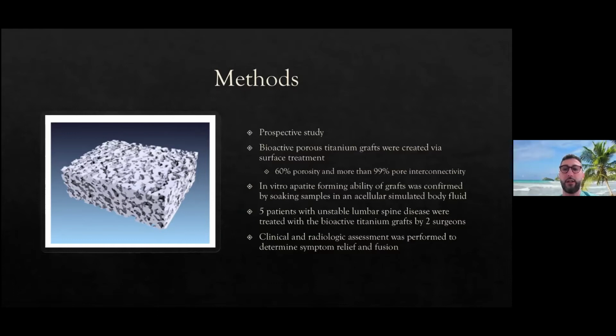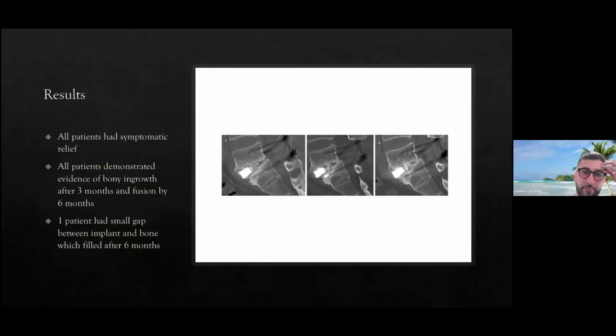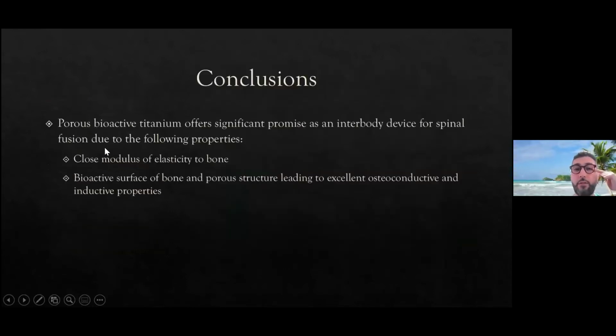And then they actually put these grafts in 5 patients with unstable lumbar spine disease, and they did a clinical and radiologic assessment. And basically all patients had symptomatic relief. They had evidence of bony ingrowth after 3 months and fusion by 6 months. And they showed this one patient who had a reasonable gap between the inferior aspect of this end plate here and the graft. And they showed that graft filled in after 6 months. So their conclusion was that this porous bioactive titanium had significant promise.